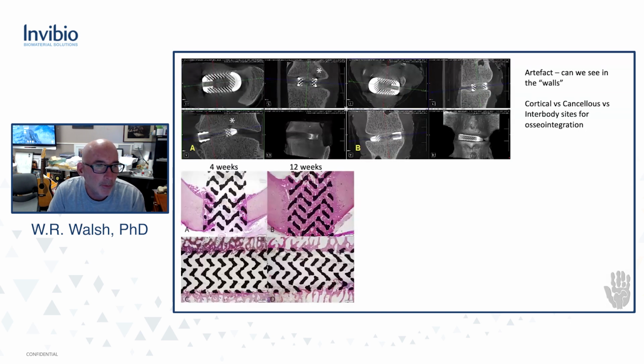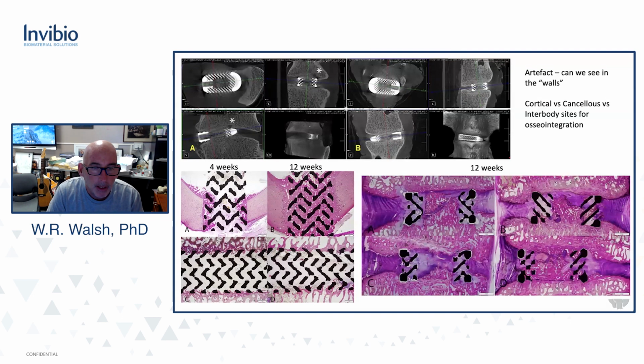So it's very difficult. When you look at the in vivo reaction in a cortical site at 4 weeks and a cortical site at 12 weeks, we get osseointegration. Cortical bone wants to be bone. But when you go in cancellous bone at 4 weeks and cancellous bone at 12 weeks, there's really no driving motivation for the bone to integrate through that architecture of the 3D printed substrate, even though the bone does love titanium. It loves the titanium at the interface. And if we look at the interbody fusion histology, again, this will be reflective of what you see in our current study. There's really not a lot of bone in the walls.